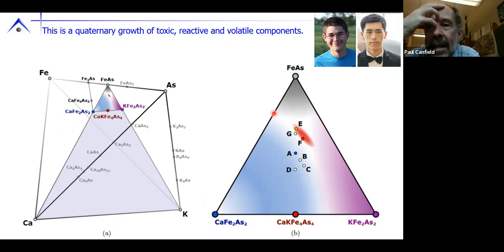So for insulators, okay, you said insulators, let's start with semiconductors. So a semiconductor, if it's a simple semiconductor, it's how long you can get an Arrhenius behavior with a large gap that you don't roll over into an impurity band or something like that. That's what we were seeing, for example, when I looked at cerium-3 bismuth-4 platinum-3, which I think is still the cleanest Kondo insulator. Now, samarium hexaboride, that's true, but some people think that it rolls over into this flat band that Megan and others saw that's associated with a topological state. On the other hand, you worry about inclusions.